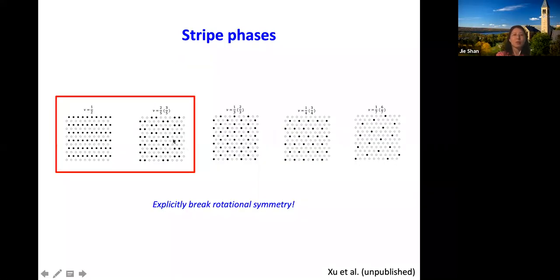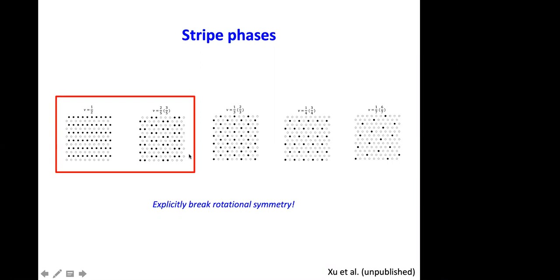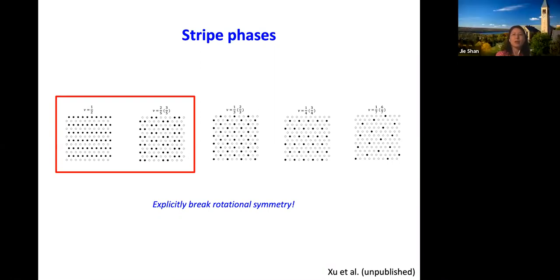Just to give you one example, if you look at those patterns, at 1/3 and so on, they still have this rotational symmetry. But if you look at the particular half filling, they form chains, so the rotational symmetry is broken, and this likely gives you different properties. Then the question is how do you probe this, and so on. So I hope this gives us a hint that the interaction effects are very strong in this system, and it's super rich.